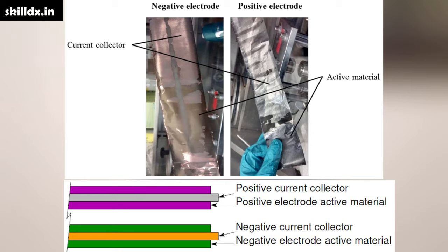In actual electrodes the materials are usually gray or almost black in color and are hard to tell apart by eye. So even though the electrodes for different form factors of lithium-ion batteries are made in similar ways, the way that they are actually assembled into the battery cells differs depending on whether we are constructing a prismatic, cylindrical, or pouch cell. Inside a pouch cell the electrodes are stacked on top of each other, whereas inside a cylindrical or prismatic cell they are wound in a spiral.